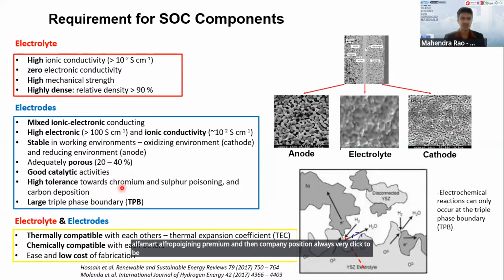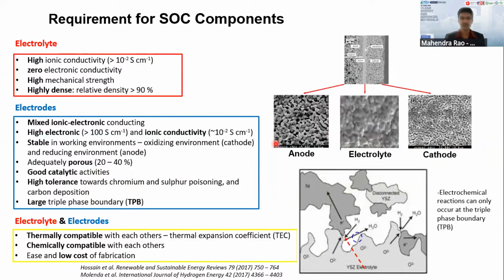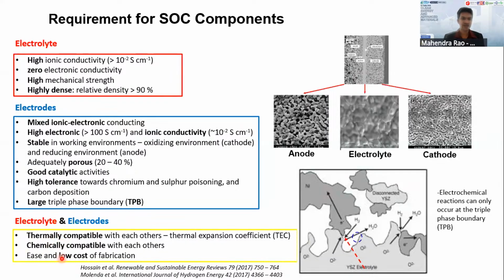So mainly the electronic conductivity is very critical for the electron movement and then the ion movement, because the TPB areas are very critical for the electrodes on both anode and cathode side. So that's why the mixed ionic and electronic conduction behavior is very critical, and the tolerance towards sulfur poisoning, chromium, and then carbon deposition are also very critical to be considered when we use the materials and also for the operating of the fuel cell at any specific operating temperature. So eventually both the electrolyte and electrodes are very critical.